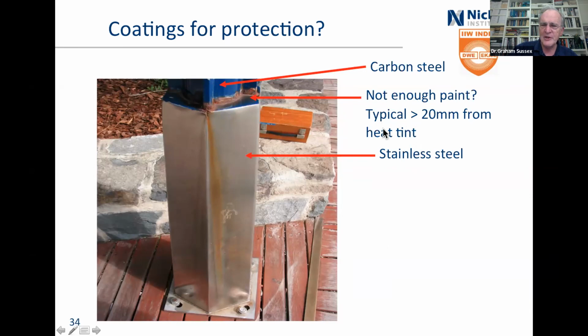But typically, you need perhaps 20 millimeters. Remember that diagram I showed, how far you can spread, how far you can throw the effect? It works both ways. If you're trying to protect, it's good. If you're worried about corrosion, so if you're worried about this acting as the cathode and there's the anode and there's no paint on it, then you have to go a further distance away, greater than 20 millimeters, maybe up to 50 millimeters, just depends how corrosive the environment is.